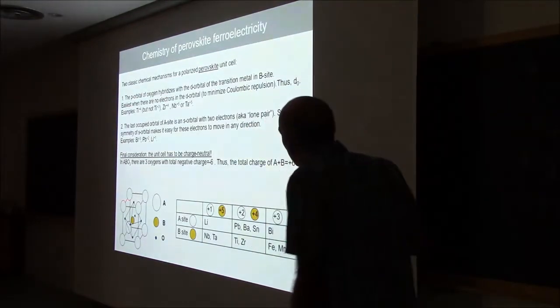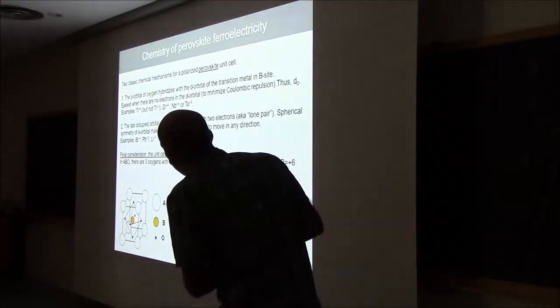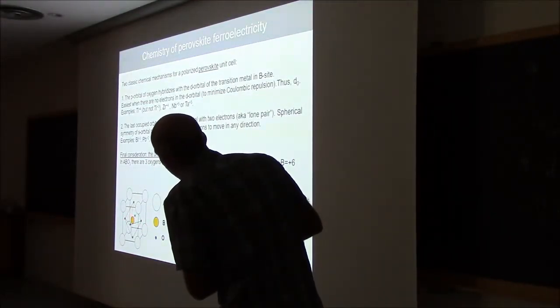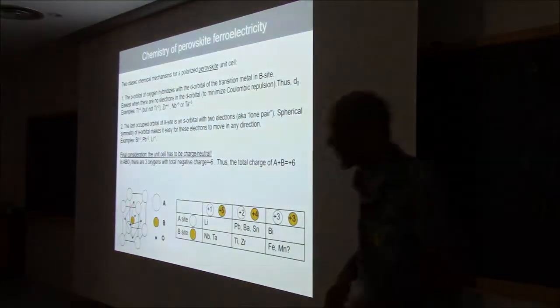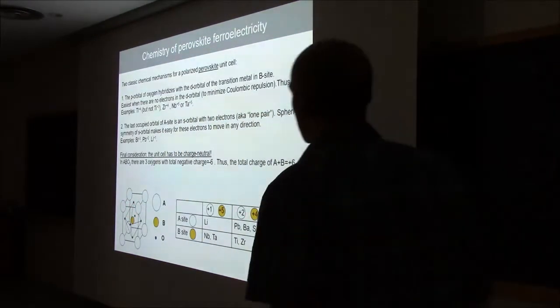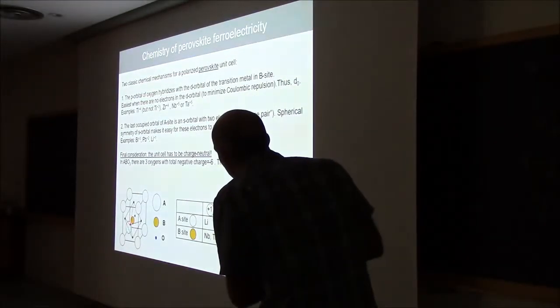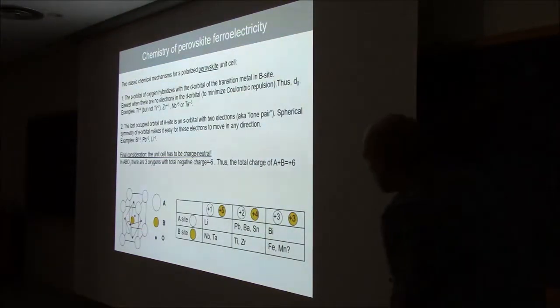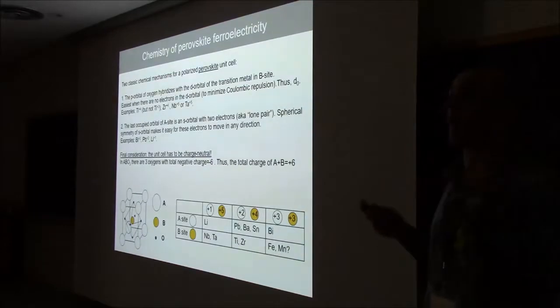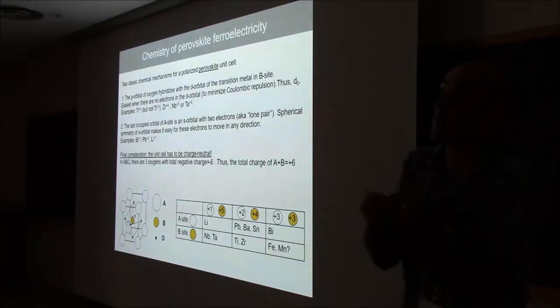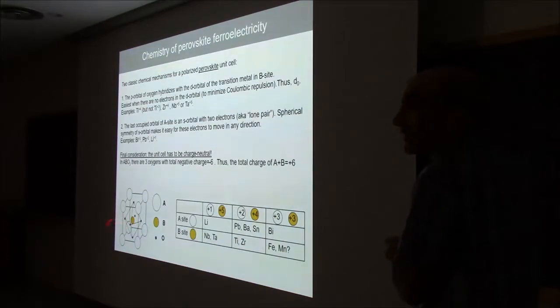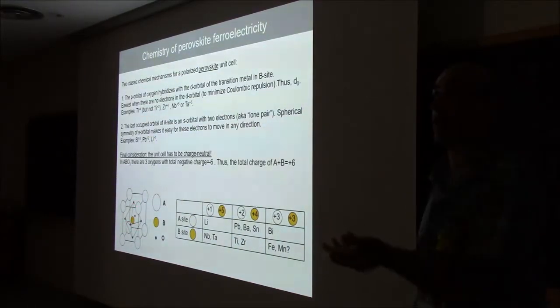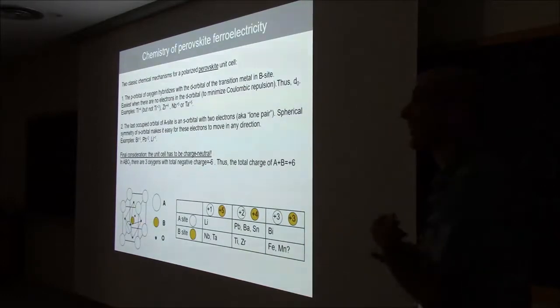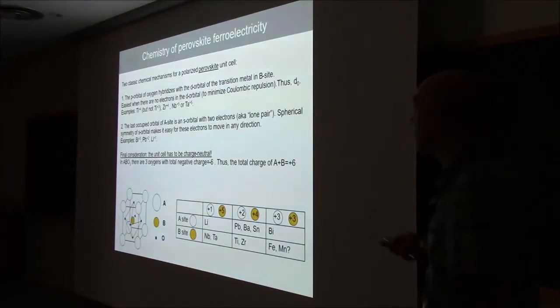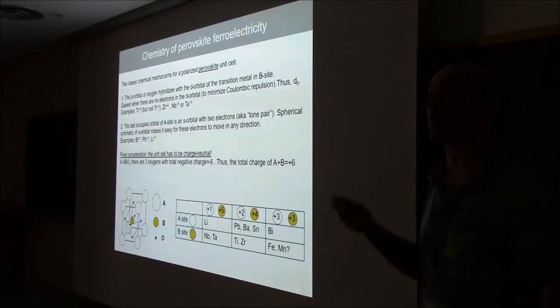Okay, so for polarization to happen, you want this ion here to go towards one of the oxygens. So you want them to hybridize. Well, that's one of the situations in which you can have polarization. For that to hybridize with the oxygen, one way in which this is facilitated is if this transition metal atom has the d orbital empty. If there are electrons in the d orbital, then there's electronic repulsion between the electrons in the d orbital of this and the electrons in the oxygen, so it's not going to move towards the oxygen. But if it is empty, then the hybridization happens more easily, and so this will shift towards one of the oxygens.